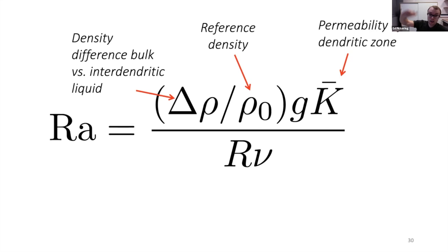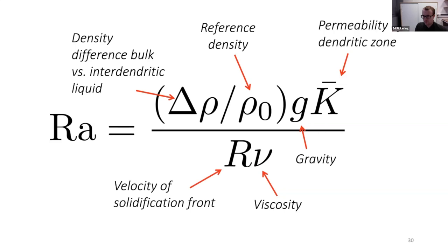It's also gravity. There's the viscosity of the liquid. So the higher the viscosity, the less likely the fluid flow is going to take place, and the less likely you are to form channels. And then finally, you've got the velocity of the solidification front. So if you solidify something really, really quickly, you don't allow these channels to form. You don't give time for the fluid flow to take place, okay?